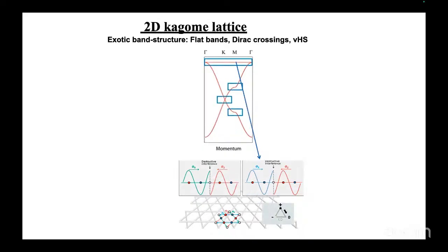Looking at a simple 2D Kagome tight binding model of the Kagome lattices, the band structure holds the flat bands and the Dirac crossing, the Van Hove singularities. The presence of this flat band in this lattice is itself very peculiar and interesting because it arises truly from the lattice. So from the destructive interference that comes from the electron hopping on the lattice, these flat bands arise. And this is just one side of the story.